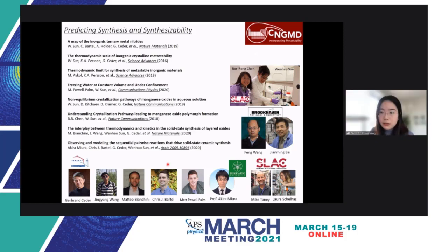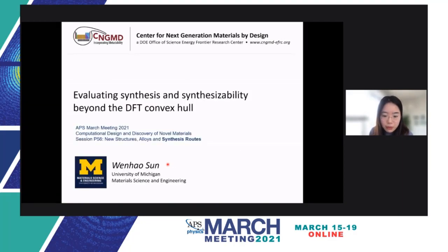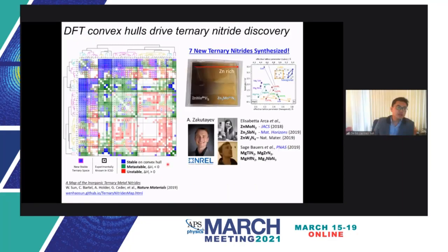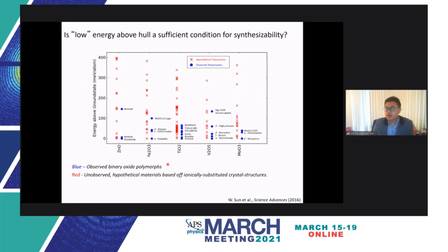We have one last minute. Another question, going back to your example of TiO2: how would you try to predict which of the hypothetical structures are synthesizable, and which phase diagram would you construct? Sure. TiO2 is one of the very famous examples where anatase, rutile, and brookite have size-dependent phase stability. Now, DFT, by the way, incorrectly predicts anatase as the ground state phase, so there are some other DFT errors in this space. So let's pretend DFT were perfect. If DFT were perfect, there's still this size-dependent phase stability that stabilizes the lowest three energy ground state phases.